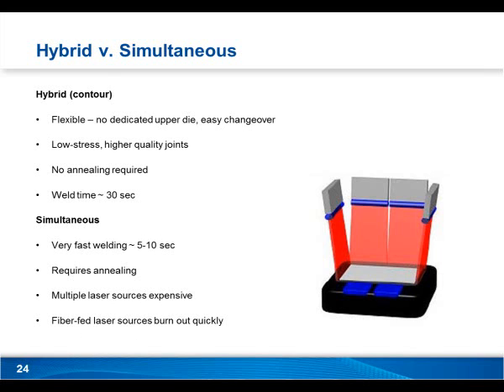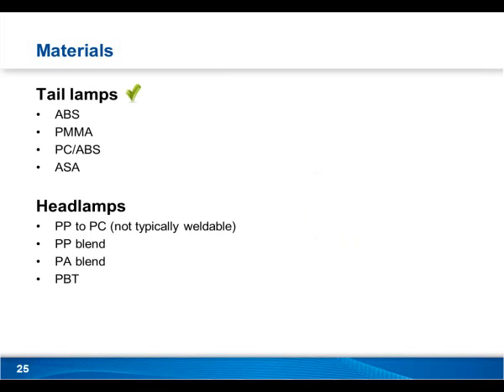Talking about materials really quick, laser plastic welding can weld virtually any materials that can be welded by other methods, and then some. So with tail lamps, ABS, PMMA, PC/ABS, and ASA are the typical ones. Headlamps, I'm bringing this up because headlamps are not typically weldable. PP to PC just doesn't work.